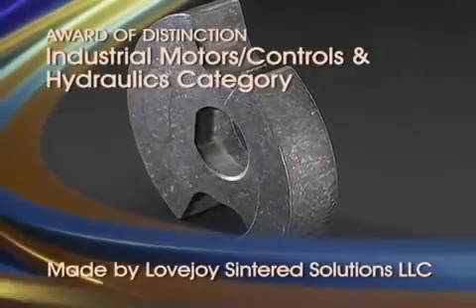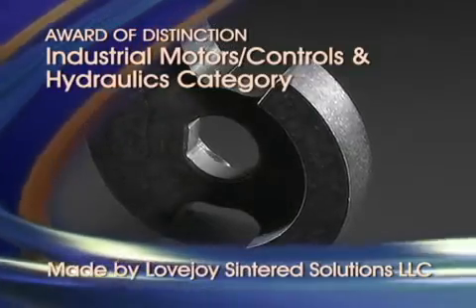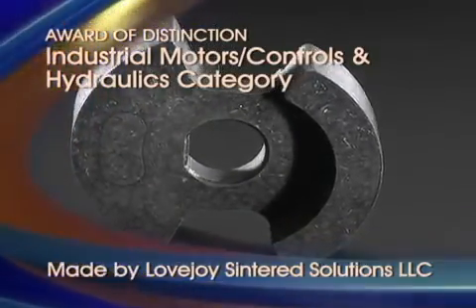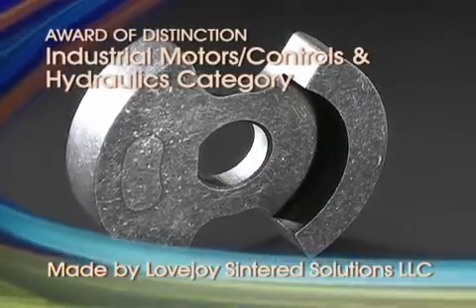Lovejoy Sintered Solutions LLC has received 2 awards of distinction in the Industrial Motors, Controls, and Hydraulics category. The first award is for a rotating machine counterweight used in a refrigeration compressor for truck trailers. Formed to a density range of 6.7 to 7.0 grams per cubic centimeter, the PM steel counterweight has a tensile strength of 47,000 psi and a 57 to 60 HRB hardness.